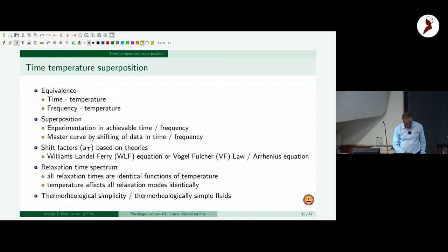Yeah, so temperature affects all of the relaxation modes identically. And in the temperature range in which this master curve preparation is being done, there are no transitions that fundamentally alter the mechanisms in the material. For example, with a crystallization event, below and above a certain temperature the relaxation processes would be very different.